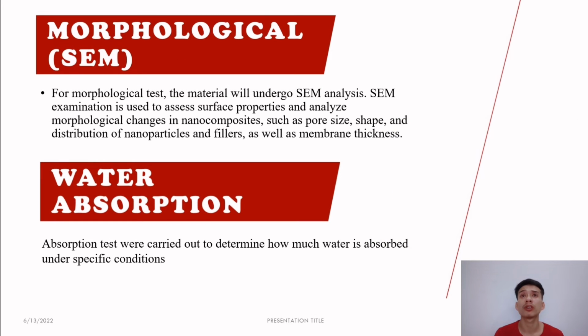Then we proceed with morphological tests. For morphological tests, the material will undergo SEM analysis. SEM examination is used to assess the surface properties and analyze morphological changes in nanocomposites, such as pore size, shape, and distribution of nanoparticles and fillers, as well as membrane thickness. After that, we follow with the water absorption test. The water absorption test is carried out to determine how much water is absorbed under a specific condition.